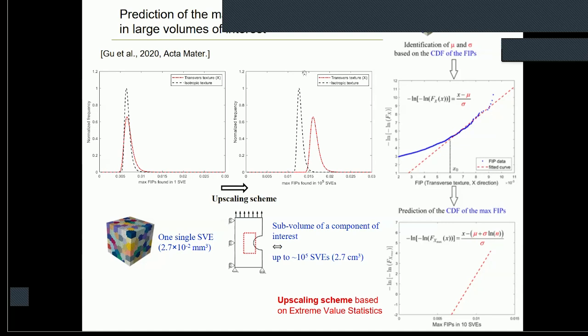For example, you can see from this structure that the volume should be something like 10 to the fifth power SVEs, or even larger. So you can see that the maximum value of the FIPs is redshifted. In other words, it will display a larger maximum value of the FIP.